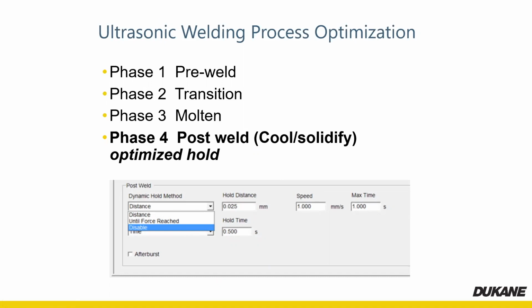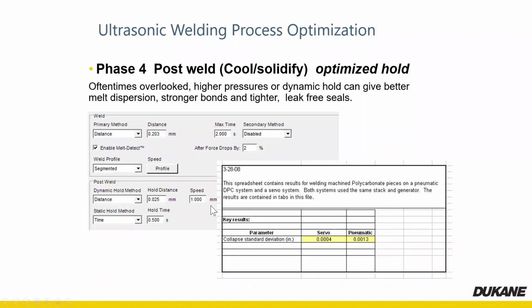So it's not atypical for us to collapse another 1 to 2 thousandths of collapse distance while that plastic is still molten. I can speed up from what I was just welding at and squeeze that last little bit of plastic into its final form for that little bit of time, and then we go into a static hold. So again, you can see here in the post weld, I've got a hold distance of 0.025 millimeters, so I'm squeezing it a little bit. My weld speed is 1 millimeter per second. My hold speed is 1 millimeter per second. My previous weld speed was 0.2 millimeters per second, 0.203 millimeters per second. So you can see I'm speeding up this last little bit of plastic. I'm squeezing it really quickly before it completely solidifies. But then I'm going to sit and not move any further. I'm going to sit stationary.